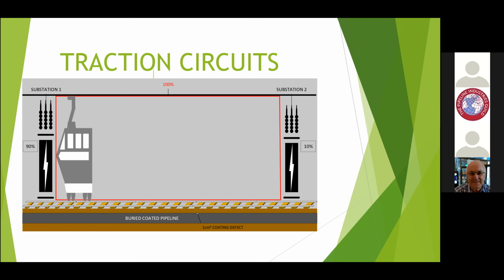Another thing to bear in mind is that, of course, normally you have an up line and a down line on a railway system. And the interference on this coating defect will also be affected by the train on the other line. And that interacts with the magnetic field with the trains on this line and the harmonics generated by both trains. So you can imagine that you get quite a complicated pattern, which is different from when the trains are approaching each other or departing from each other, or they're both at the same time in the same place. It really is quite a complicated state of affairs.